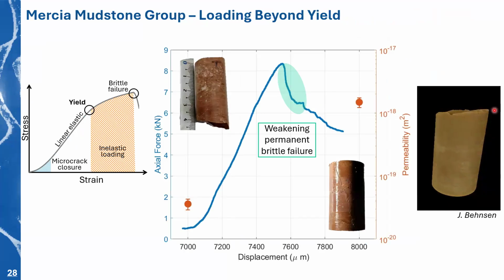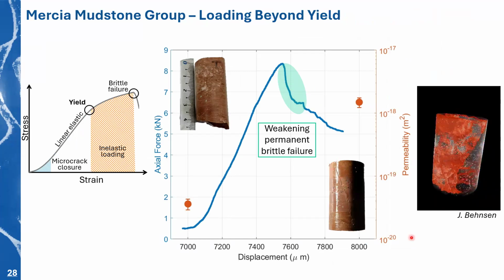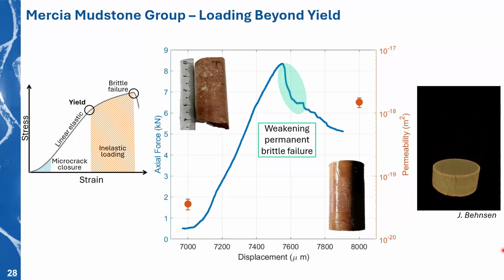I also did the loading beyond yield. This is technically for a different one, a different Mercia Mudstone sample, but I wanted to show it. So we see that the intact sample is up on the top left, and then after it loaded, after it broke, we had quite obvious macro fractures through it. So I gave the sample to Julia over in the SEM labs, and she did a micro CT scan of the sample, so you can see here. So it shows that we can actually see the macro fractures in this sample after it was broken.